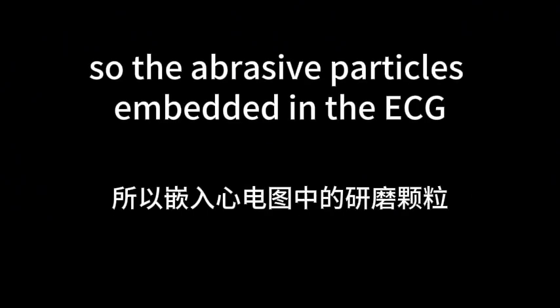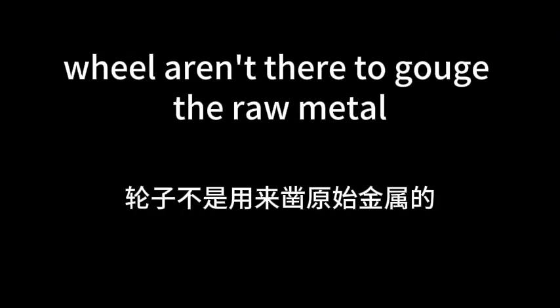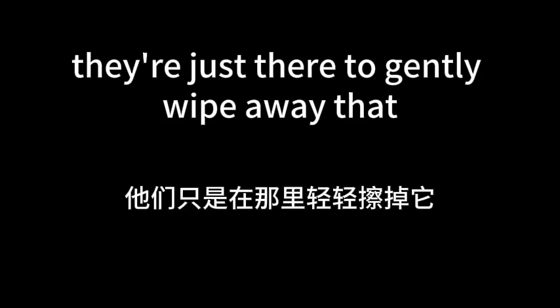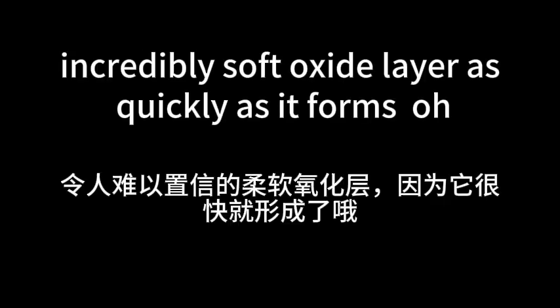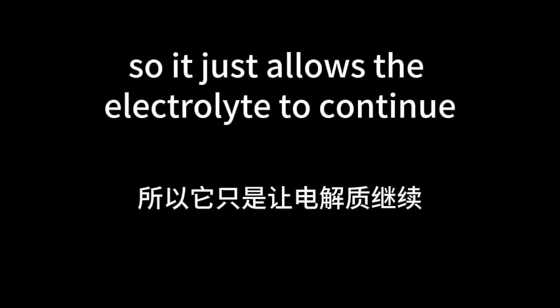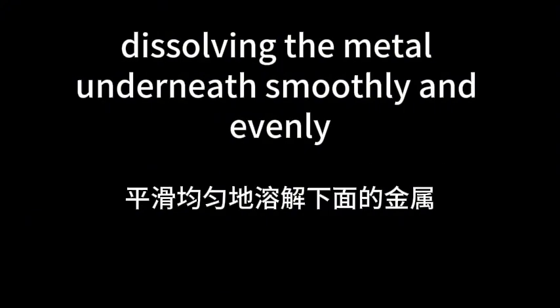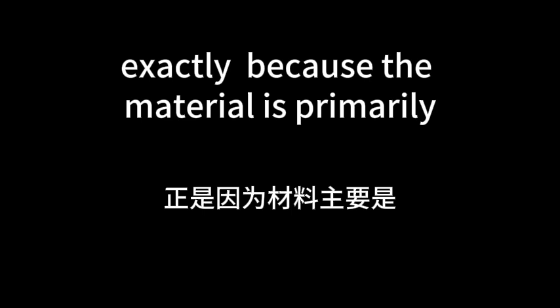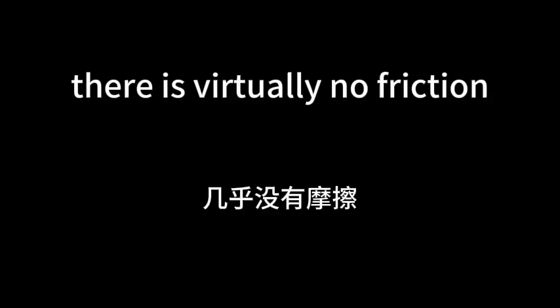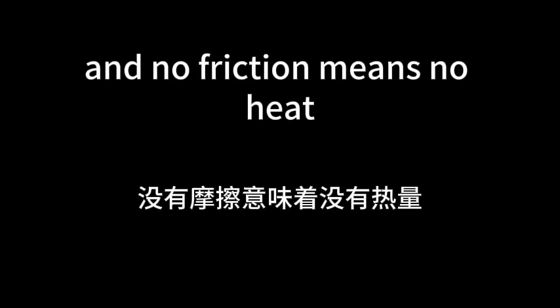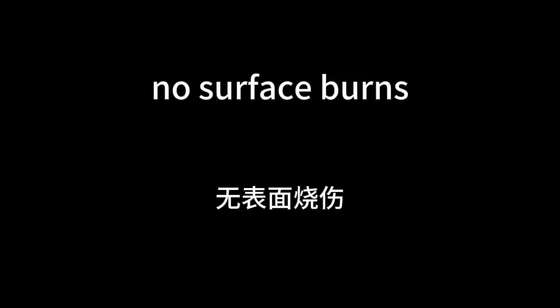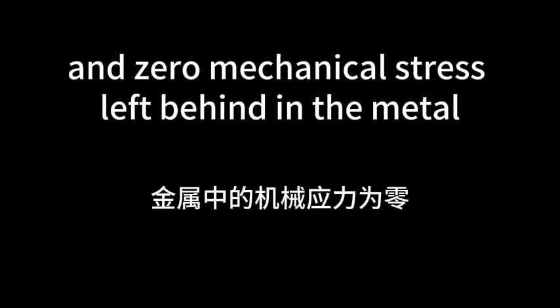Right. So the abrasive particles embedded in the ECG wheel aren't there to gouge the raw metal. They're just there to gently wipe away that incredibly soft oxide layer as quickly as it forms. Oh, so it just allows the electrolyte to continue dissolving the metal underneath smoothly and evenly. Exactly. Because the material is primarily removed electrochemically, there is virtually no friction. And no friction means no heat, no surface burns, and zero mechanical stress left behind in the metal.